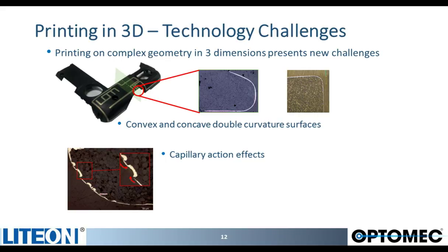Sometimes for a molded structure, the surface is not as smooth as you would think. The surface can have pit holes and other surface defects that cause challenges during printing. In these holes and voids, we have seen capillary action happen, and the ink is pulled down into the openings, leaving a very thin conductive layer on the top surface. The quality of the molding, the print process, as well as the ink behavior, are very important factors.